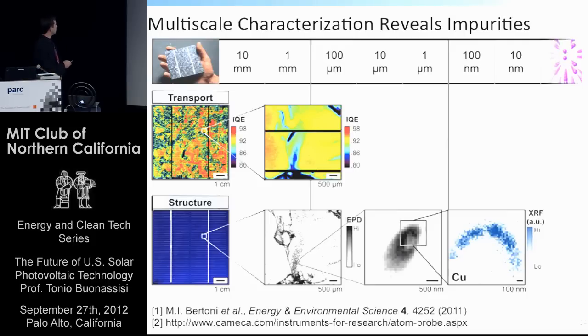These are electrical tools using a laser to raster over the solar cell device, a real macroscopic solar cell device, and measure the current output at each spot the laser strikes. So you're measuring a map of the electrical performance on the device. We call it electrical transport properties. This is a structure. As you zoom in, you can etch the material to reveal certain defect structures. Here you can see these defects, these dark spots, dislocations, correspond to regions of lower performance.